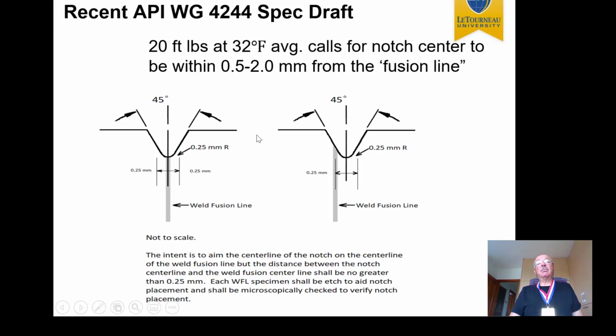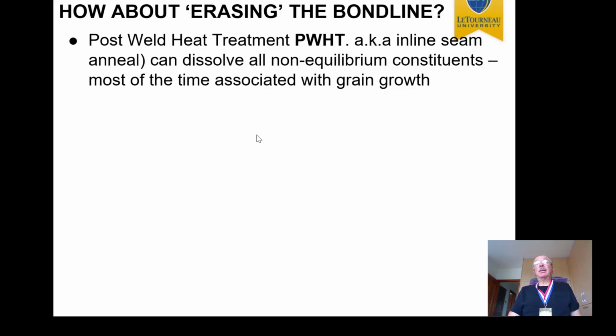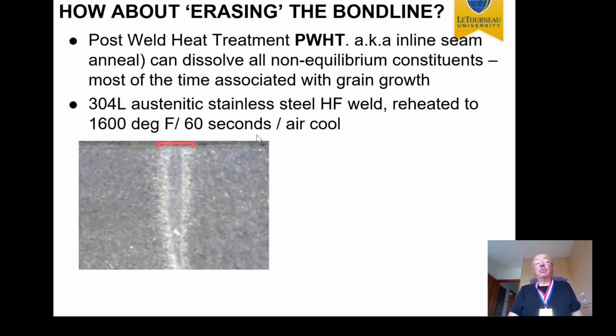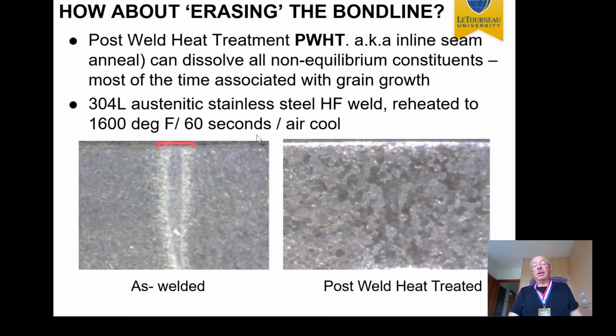And people recognize that. The recent API spec shows that if they want to establish the toughness of an ERW weld, they should place the notch somewhere around the bond line, 0.25 to the left or right. Regardless, they recognize that the so-called fusion line is really not that important. So, if somebody is really bothered by these bond lines, they can erase them, because post-weld heat treatment, the so-called inline seam anneal, can dissolve all these constituents. And so you end up, for instance, in this case, with 304L austenitic stainless steel, reheated and then air-cooled. You can see that before, as welded, you have that ferrite bond line, and post-weld heat treated, it completely disappeared, showing that it's neither decarb, nor inclusions.